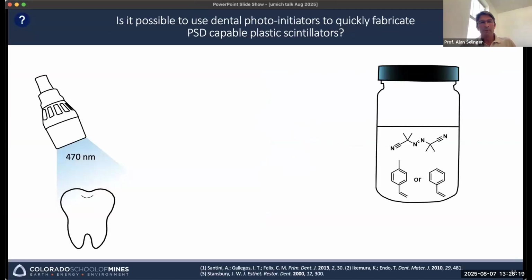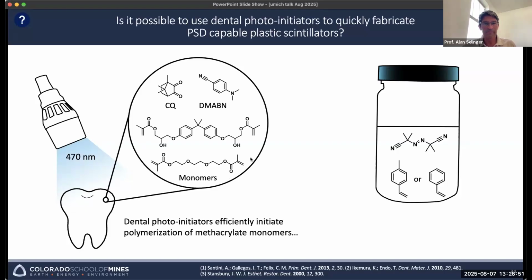So maybe some of you are aware or have had some cavities in your teeth. And most of the processes used nowadays are light photo-induced polymerization of these materials into your cavity. So it's basically a methacrylate or styrene functionalized material that is now used in conjunction with a photo initiator rather than a thermal initiator. And so this is what is used in dental composites. It's some kind of a methacrylate monomer, some silica filler, and then the light is put into your mouth, focused on that cavity where the material has been deposited, and it is photopolymerized.